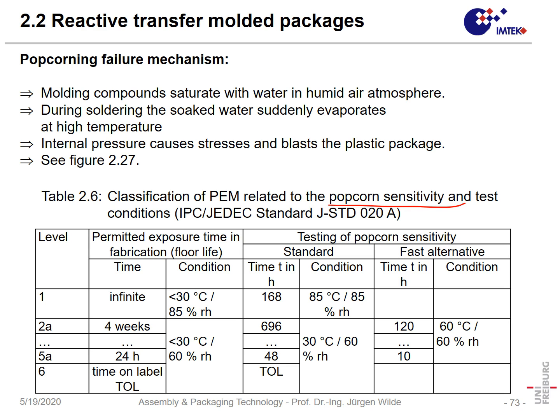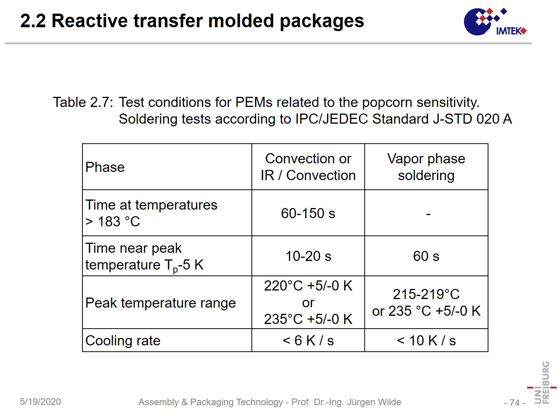and here you have no acceleration, and that means you have to test for a very long time, but there are certain alternatives to make this test faster. For instance, if you want to go from 700 hours to 120 hours, you can increase the temperature by 30 degrees. Of course, when you do this testing, also the soldering process is part of the testing procedure. And that means the standard which describes a popcorning test also describes how you have to perform the soldering.